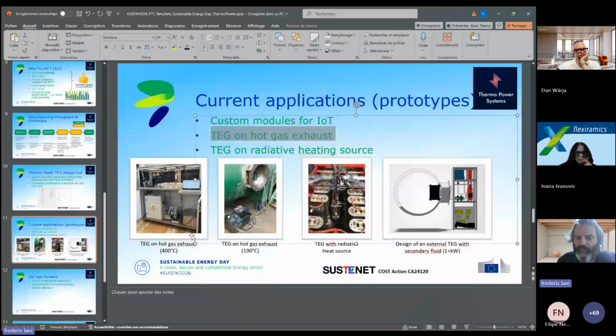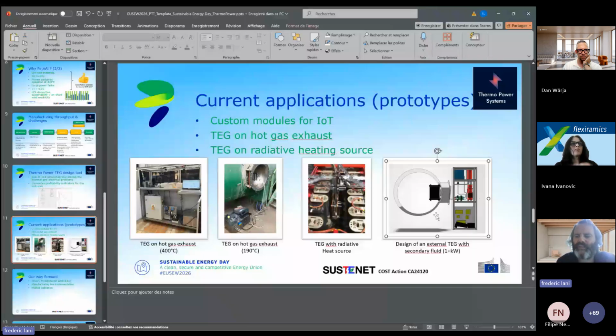On the left, it's for a temperature of 400 degrees C. The second picture is on a waste burning site, where we have hot gas exhaust of 190 degrees C. So this is a proof of concept, and we are now developing what you see on the right. The idea is to really extract the calories from the hot gas exhaust and have an external thermoelectric battery. We call this thermoelectric battery, maybe it's a bad wording, but it's how we call it. We try to use as many very standard elements as possible, that you could find in other waste heat recovery technology, to really minimize the cost.